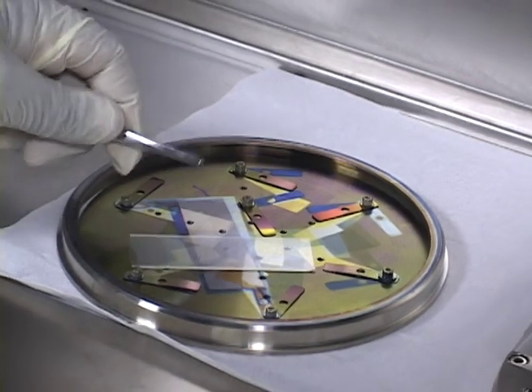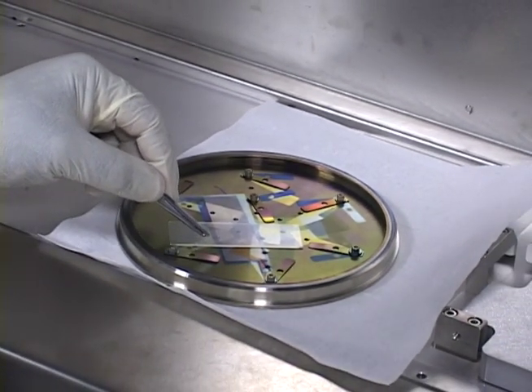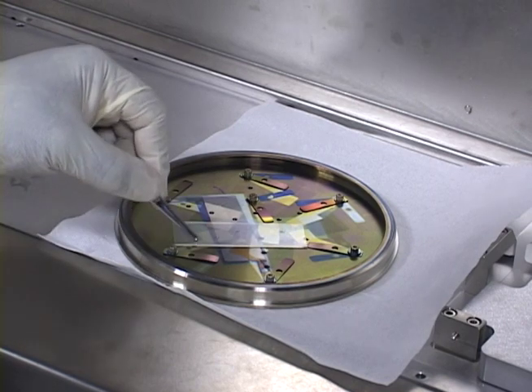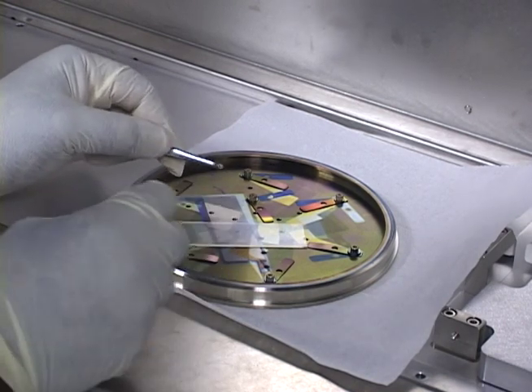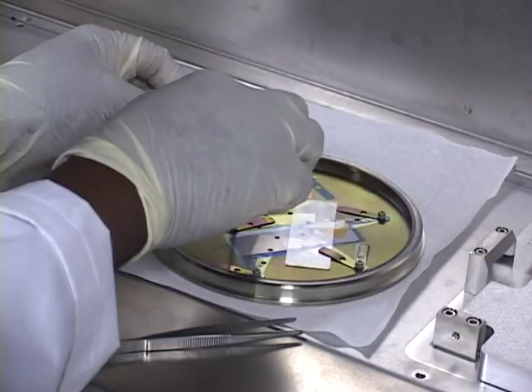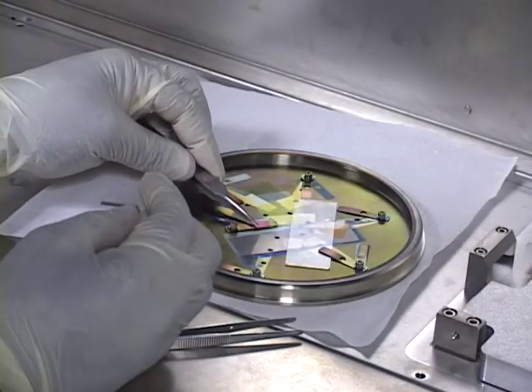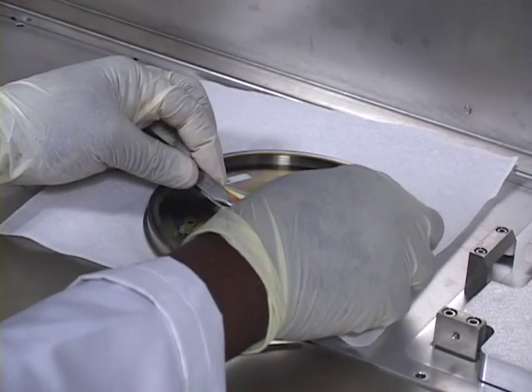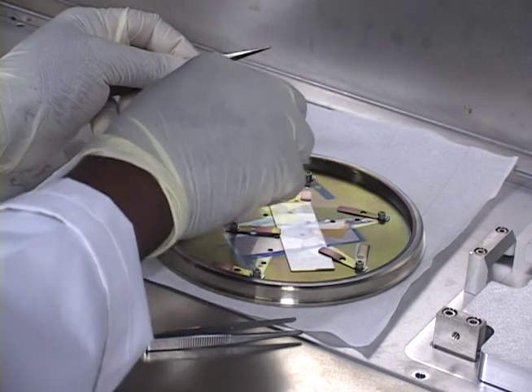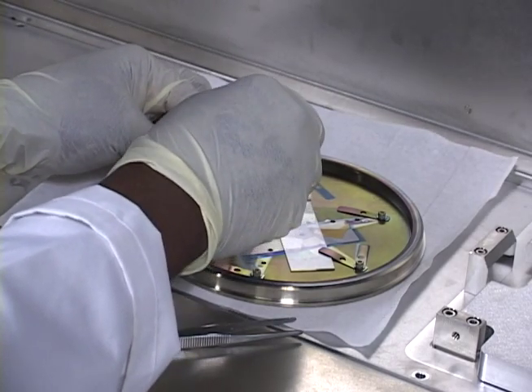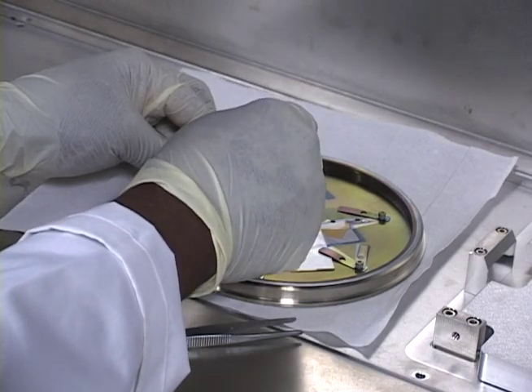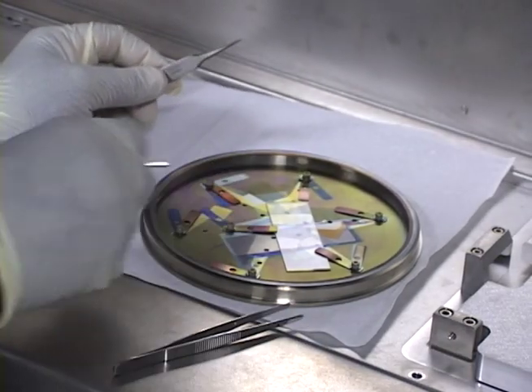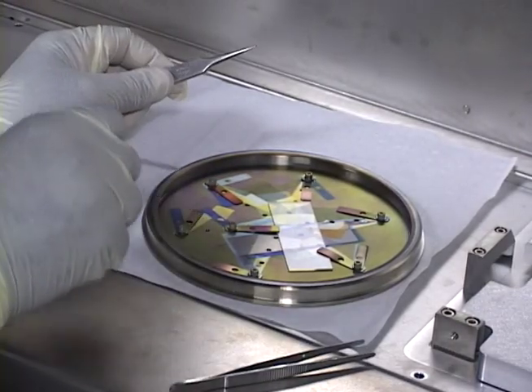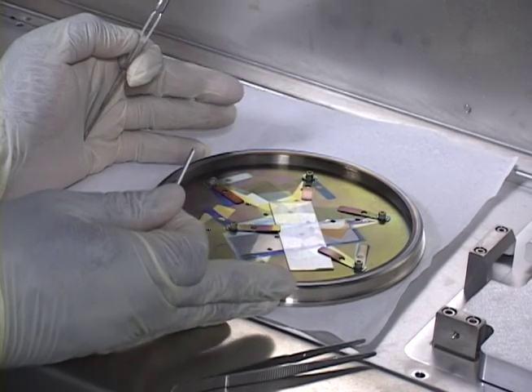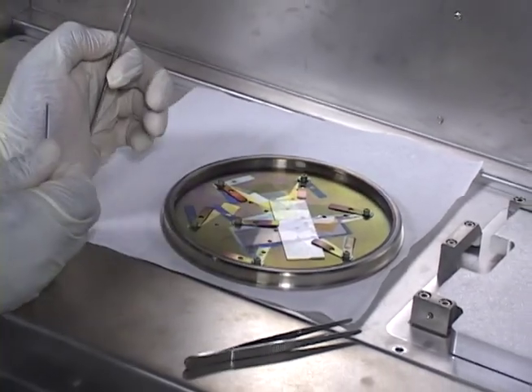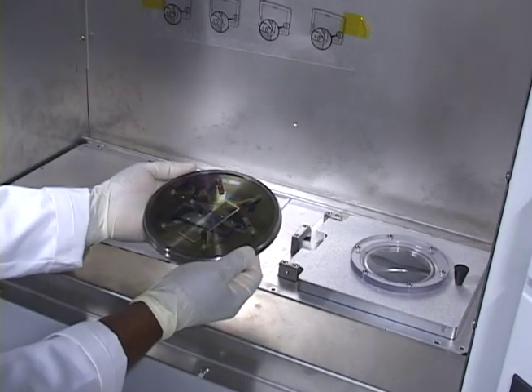This is a microscope slide. We're going to use about 3 screws to fasten this piece down so it doesn't move under deposition. This particular piece of machine can be used for manufacturing purposes on a large scale, whereby you can deposit a number of thin films at one time, say within 15 to 20 minutes. Also, this particular sample holder can hold a minimum of 4 to a maximum of about 6 slides, and that is good for not only research purposes but also for manufacturing purposes on a very large scale. We've mounted our sample onto the substrate.